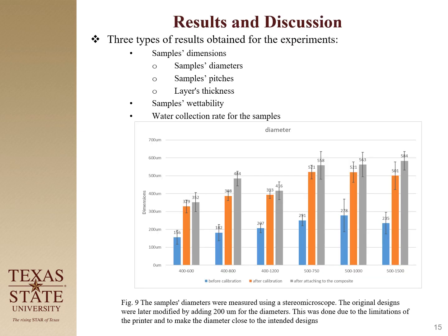Now the results. I divide my results into 3 parts. One is dimension, one is wettability, and finally the water collection rate for the samples. So I measured the diameters and the pitches of the sheet after printing, and I found that the diameter was always smaller than my intended design. So I ended up changing the CAD file for each diameter, increasing it by 200.